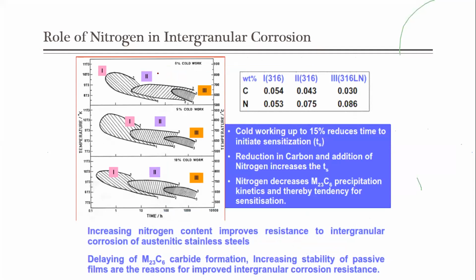And coming to the intergranular corrosion, here you can see the TTT diagram, that is time, temperature, and transformation diagram, for 0% cold work, 5% cold work, and 10% cold work samples here. The carbon and nitrogen contents have been taken here. The first one indicates 0.054% carbon and 0.053% nitrogen, that is 316 alloy. In the 316 alloy, they have designed for different amounts of carbon and nitrogen. For the second alloy, they have chosen 0.043% carbon and 0.075% nitrogen. And for the third alloy, they have chosen 0.03% carbon and 0.086% nitrogen over here.